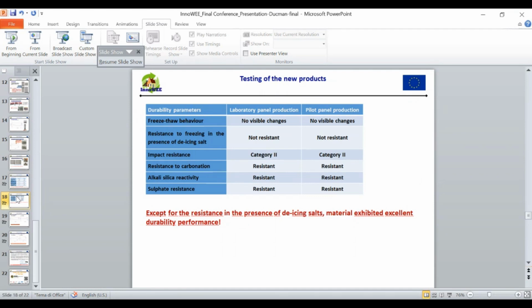Additionally, durability tests have confirmed that the newly developed products are resistant to freezing, carbonation, alkali silica reaction, and also eventual sulfate attack. Products are not resistant if exposed to freezing in the presence of de-icing salt, both in the laboratory and in the pilot production. This means, as I said before, that their use has to be excluded from environments where salt and freezing act simultaneously. And again, the results of tests from laboratory and pilot production are in very good agreement, as we will also see from the next two slides.